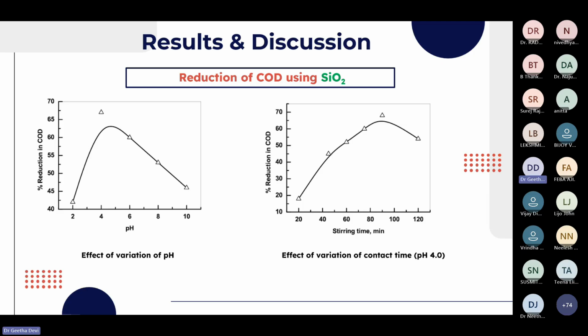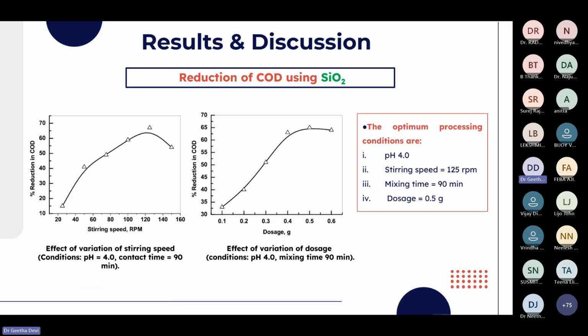We compared the efficiency of silica nanoparticles by conducting the same experiment, that is, pH, stirring time, stirring speed, and dosage were varied. Here the optimum processing conditions were obtained as pH 4, stirring speed of 125 rpm, mixing time of 90 minutes, and a dosage of 0.5.